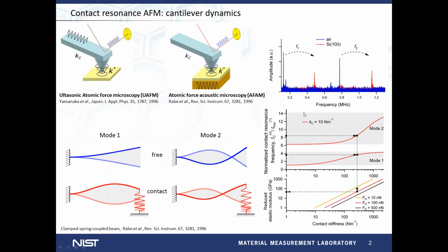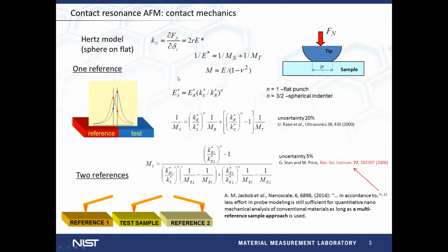the contact stiffness. The next step is to go from contact stiffness to the elastic modulus of the sample, and this is done by using the contact mechanical model that we think is most appropriate for our tip-sample contact. So a simple representation here is with a Hertz model, a spherical tip indenting a flat surface. The contact stiffness is proportional to the diameter of contact and the reduced elastic modulus. This reduced elastic modulus is a combination of the indentation moduli of the sample and the tip. The indentation modulus finally is given in terms of Young's modulus and Poisson ratio.